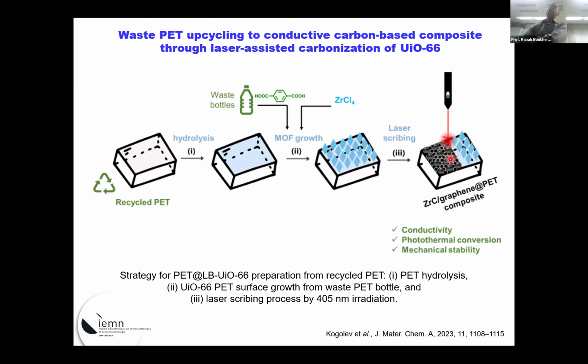Now, with the laser, we can transform this. Instead of having what you call laser-induced graphene, you would have zirconium carbide with graphene. So you have a completely different material, consisting of zirconium carbide and graphene. Of course, if you change the metal here with something else, you will have a different metal carbide, depending on the metal used here. The advantage of this is that it has a high conductivity, high photothermal conversion, and good mechanical stability.